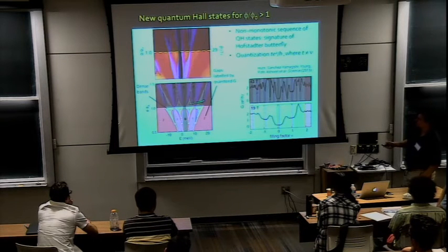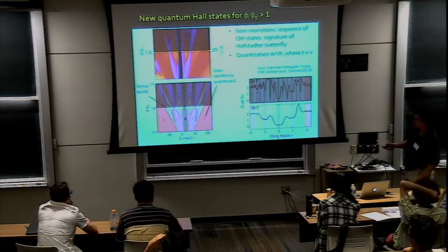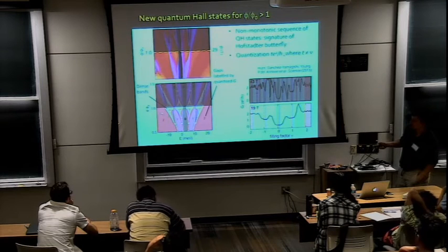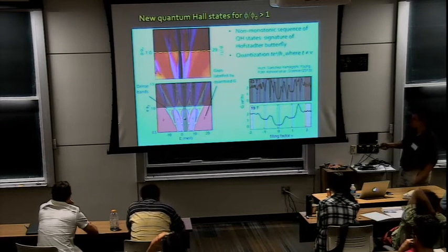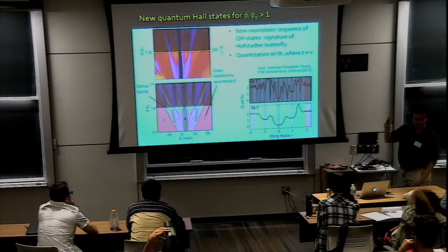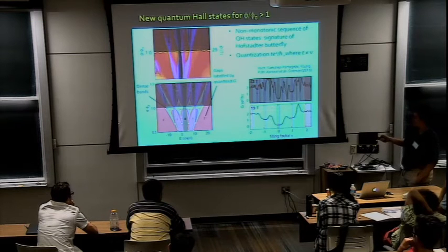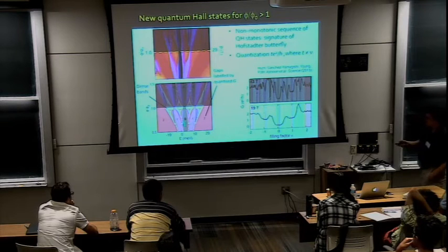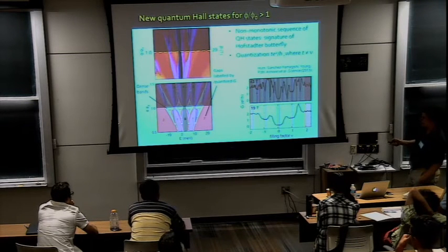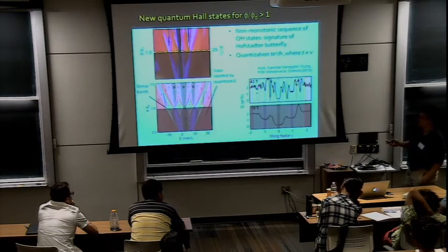Let me shade it higher. What you have, if you measure quantum Hall effect, is roughly, the Hofstadter spectrum is modifying your band structure and your quantum Hall physics, but roughly what you see is what you expect for graphene in a perpendicular magnetic field: 2, 1, 0, 1, 2. Okay? Here I mentioned these peaks have to do again with this geometry that I mentioned before. But essentially you see 2, 1, 0, 1, 2, okay, that we've seen a number of times now. If you go above 1 flux quantum per superlattice unit cell, you have this.